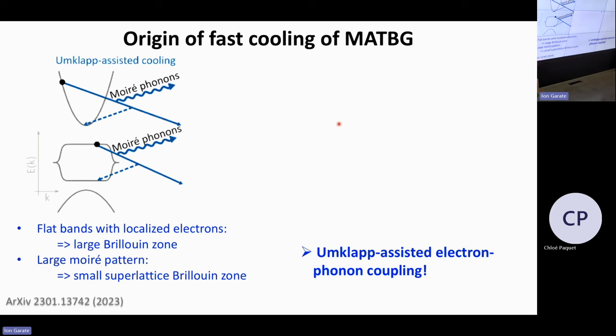So this is a bit the picture in energy momentum space. So you have these large energy electrons, and they want to couple to these very low energy phonons, with a huge momentum mismatch, and they get this additional momentum by scattering out of the Brillouin zone and then folding back, so that they can lose quite a significant amount of energy, even though they're coupling with low energy phonons. So this is the picture we had.